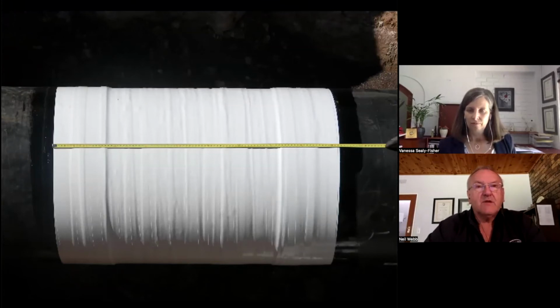And something that a lot of people don't realize is that ST2, which is the wire brushing standard, is actually a very stringent surface preparation standard in terms of the level of cleanliness that is achieved on the surface before application. And so because of the hoop stress in the tape as it's wrapped, whether that hoop stress is actually tension in the tape, or with the soft tapes like petrolatum tape, for example, it's not hoop stress, but just plain stickiness that keeps the tape in place. The chemical and mechanical bonding that we need with liquid coatings, like epoxies, polyurethanes, and so on, is not necessary.